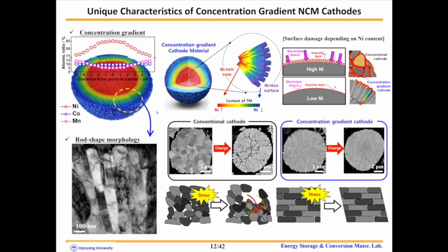Concentration gradient cathode material has unique features distinguished from the conventional cathode active material. First, as explained, concentration gradient cathode material consists of a nickel-rich core and a nickel-poor shell part. The cathode surface composition comprising high nickel content is very reactive to electrolyte attacks. The nickel-rich conventional cathode surface is easily damaged by the electrolyte attacks, forming a thick impurity layer, whereas the nickel-poor surface of the concentration gradient cathode is much more stable from the electrolyte attacks,